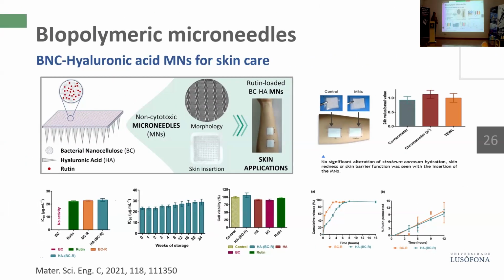And this work is a combination of microneedles with bacterial cellulose. It was work that we performed some years ago, but it was very interesting because we thought, why not use bacterial cellulose as a back layer of the microneedles, first to reinforce the needles, but at the same time use this membrane to deliver another molecule and complement the effect of the needles. In this case, we use hyaluronic acid needles and this back layer loaded with rutin.